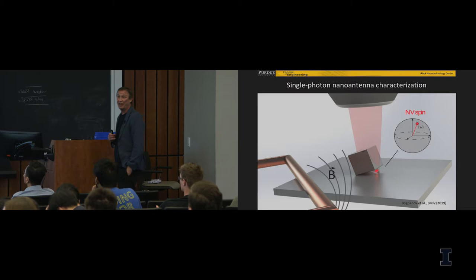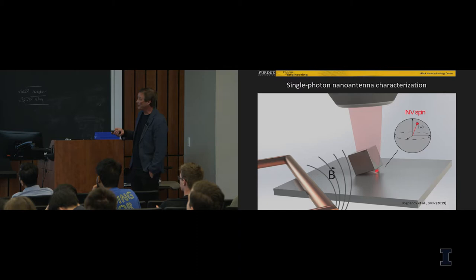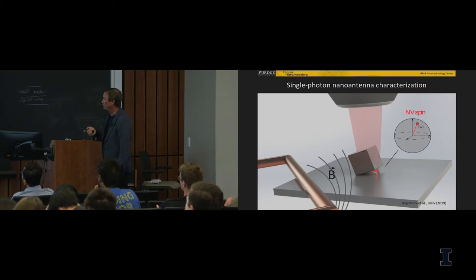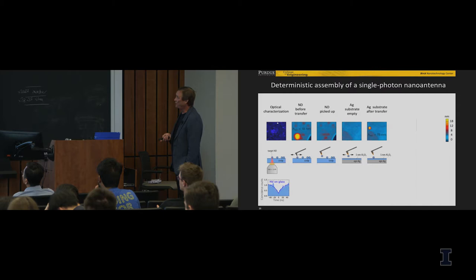So then you have a wonderful situation, because you get the largest possible enhancement. You also could excite the spin degree of freedom of your nanodiamond. And for nitrogen vacancy, the spin degree of freedom has a relatively large coherence time, which is important potentially for quantum memory. So you could excite it with microwave radiation, and you could read that spin state optically by using this light. So that's the system. That's basically how it's done.